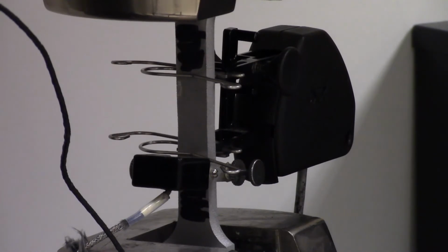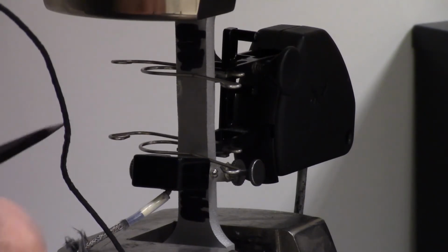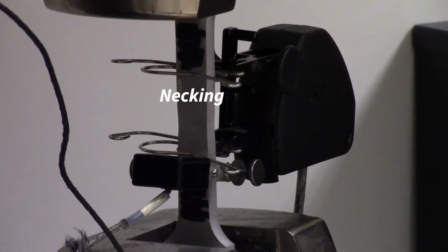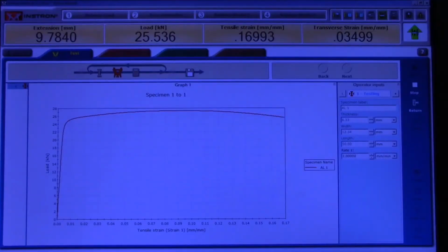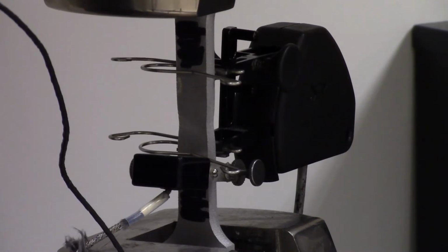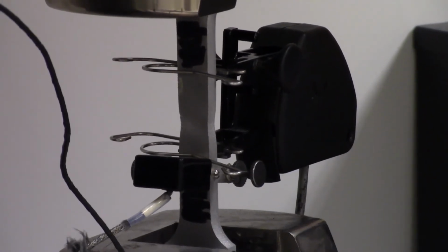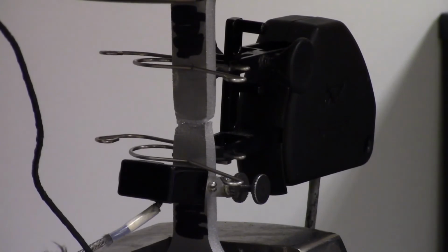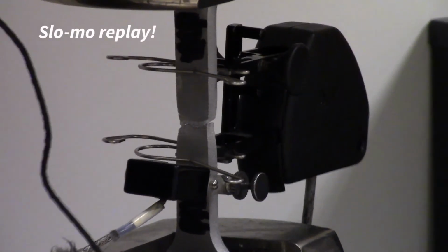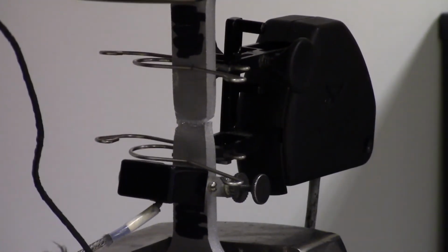It looks like it's starting to begin in our gauge section between the knife edges of the extensometer. Should be able to see it right here. If we look at our plot, we can see that the load is decreasing more rapidly now. Should be getting pretty close to fracture at this point. All right, so there's our fractured specimen. We'll pull that out and then measure between those two marks, which you can see on the specimen, and see what our final length is.